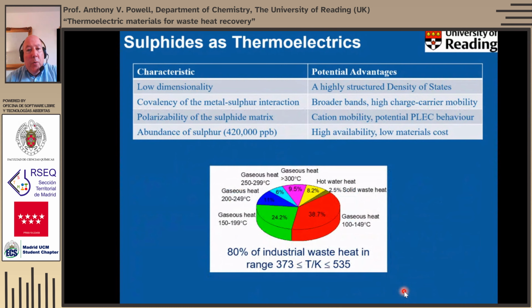And the other point really that attracts us about sulfides is that because of the sort of temperature range in which they're stable and they show high performance and so on, they're well suited to industrial waste heat. And some estimates of industrial waste heat indicate that about 80% of it is actually released in this temperature range over about 373 to 535 Kelvin. That's just a very good range for sulfides because sulfides are not especially stable at higher temperatures.